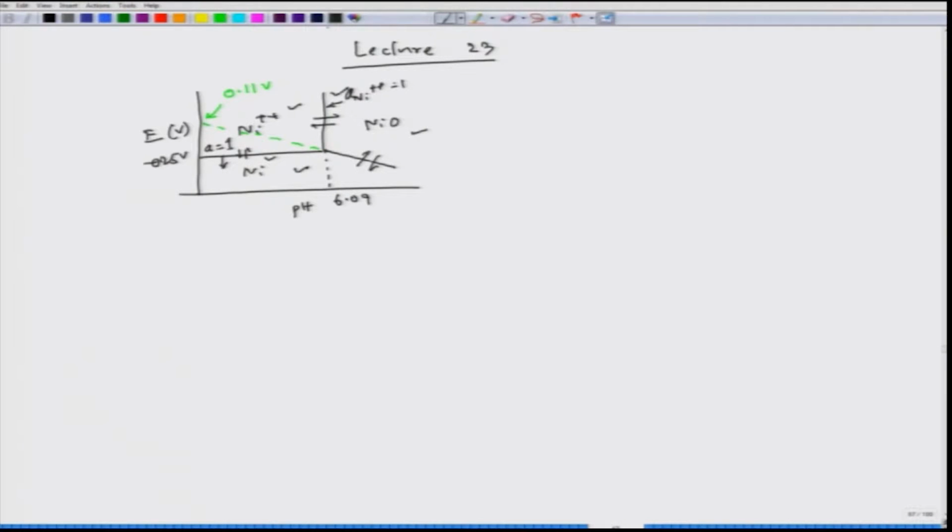And interestingly, another important aspect is that when we draw these lines according to the reactions we have stated earlier, we have to fix a nickel ion concentration. Now, if we fix this activity to be 1, then for this line we also have to see that the activity of nickel ion concentration should be 1. Now, if we change it to 10 to the minus 6, then this line also needs to be changed to 10 to the minus 6. So, it will be valid for a particular nickel ion concentration. So, this has to be fixed first, and then we need to draw all 3 lines.